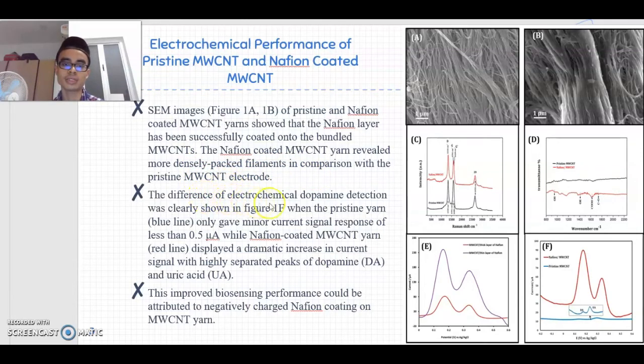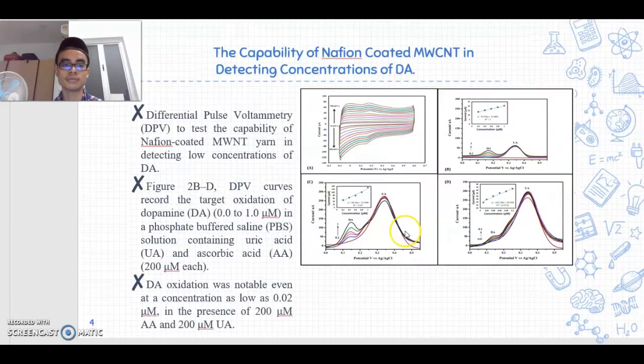The difference of electrochemical dopamine detection was clearly shown in figure 1F, where the pristine yarn, the blue line, only gave a minor current signal response of less than 0.5 microampere, while the Nafion-coated multi-wall carbon nanotube yarn, the red line, displayed a dramatic increase in current signal with highly separated peaks of dopamine and uric acid. This improved biosensing performance could be attributed to the negatively charged coating on the multi-wall carbon nanotube yarn.